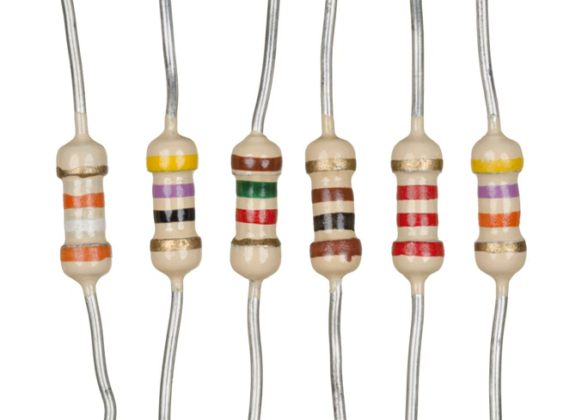Some carbon composition resistors can exhibit thermoelectric offsets as high as 400 microvolts per degree Celsius, whereas specially constructed resistors can reduce this number to 0.05 microvolts per degree Celsius. In applications where the thermoelectric effect may become important, care has to be taken to mount the resistors horizontally to avoid temperature gradients and to mind the airflow over the board.